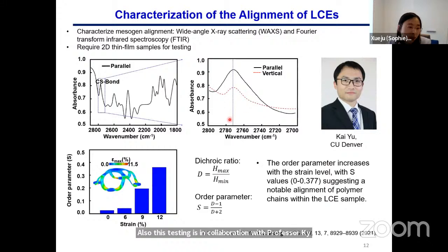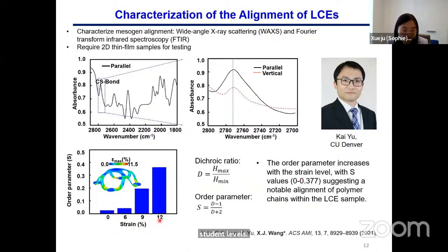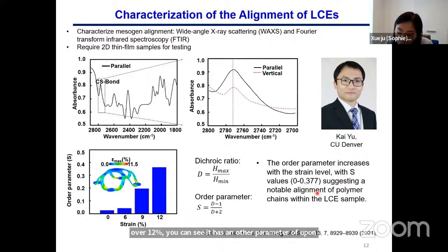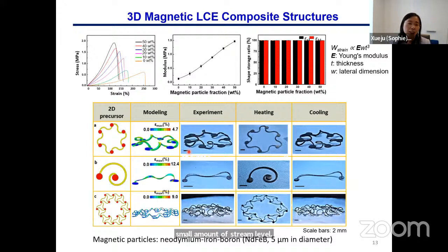So I will skip the details, but basically, we can see that the alignment degree, which is quantified by a parameter called the order parameter in LCEs, is proportional to the strain levels. Also, for example, at a strain level of 12%, you can see it has an order parameter of 0.377. For your reference, this order parameter is usually below 1. So basically, it suggested a notable alignment of polymer chains within the LCE sample already with a small amount of strain level.